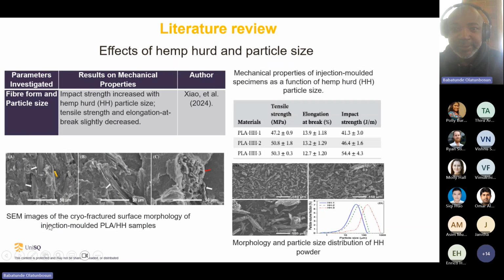In my literature review, a lot of work has been done regarding hemp, but specifically sunn hemp, few works have been done in terms of the hurd usage in hemp. Researchers like Xiao et al. in 2024 worked on hemp and particle size. They looked at the impact strength, and their results show that the impact strength increased with the hemp particle size, but the tensile strength and elongation at break slightly decreased. These are their findings. You could see the SEM image of the morphology of the part of the board made using injection molding.